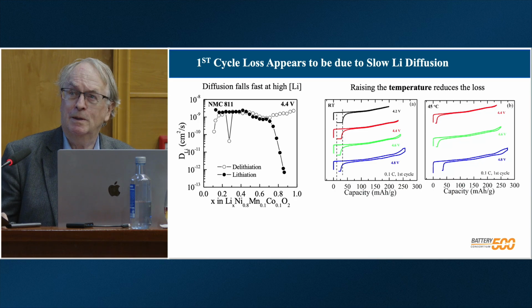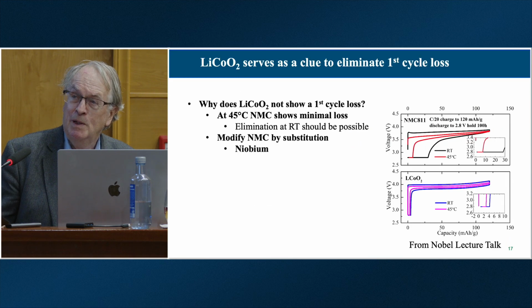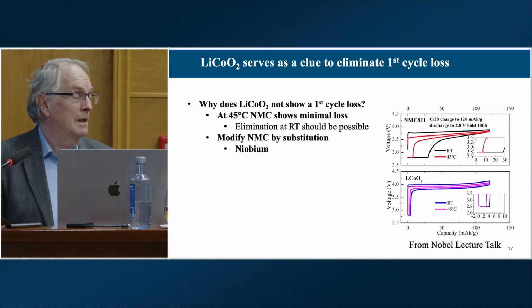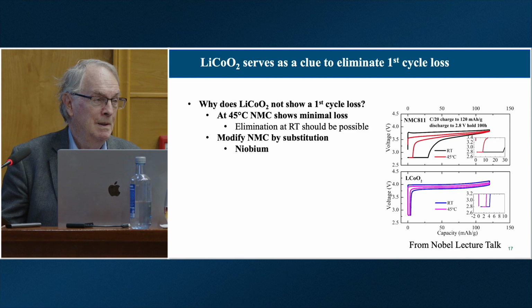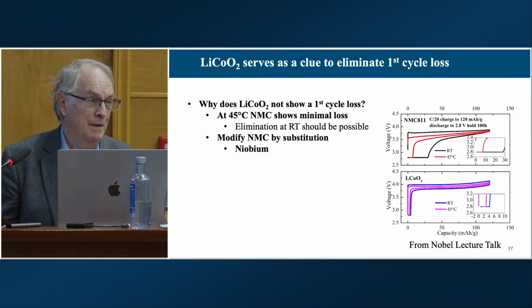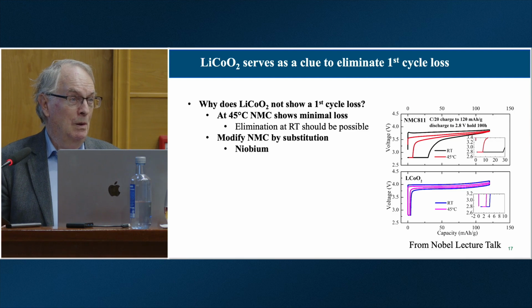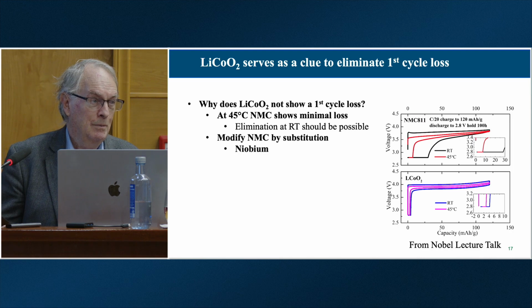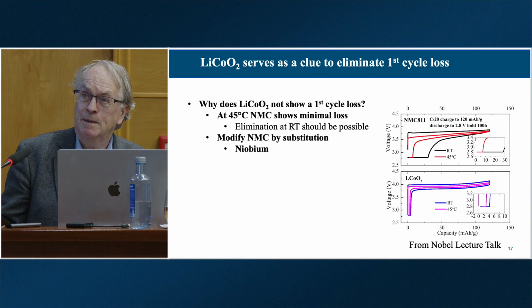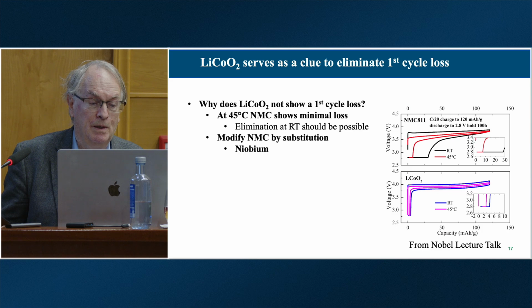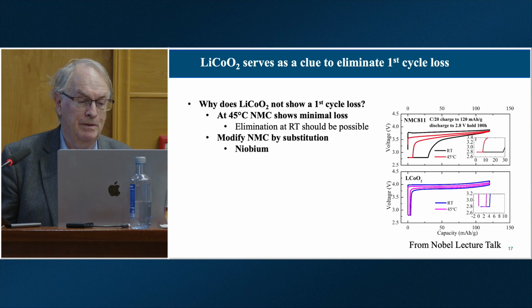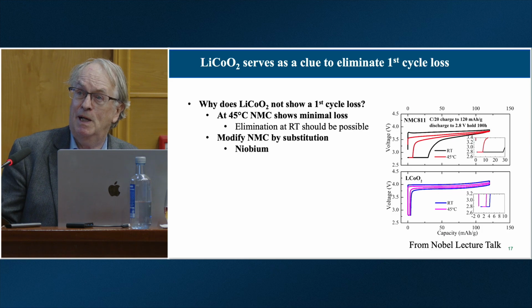So let's just look at what we can do to solve that. And the first clue you get, if you look at lithium cobalt oxide itself, it does not have that problem, which tells us if we modify our materials to make them more like lithium cobalt oxide, we should eliminate it. So I just show you 2 plots on the right-hand side, the 80% material and the pure lithium cobalt oxide.